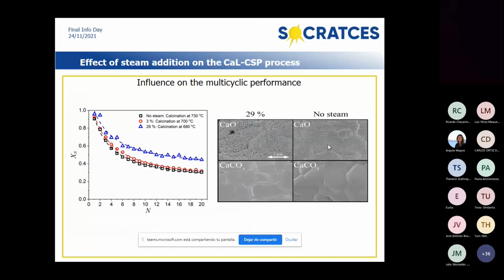As I said in the first slide, we were also interested in studying how it affects the multi-cyclic performance. What we found is that the steam also increases the reactivity of the material. In order to understand this better, we took micrographs of the sample after 20 cycles, shown on the right. And what we found is that the microstructure that we obtain using steam seems to be more open, and we think that this can explain the increase in the reactivity.